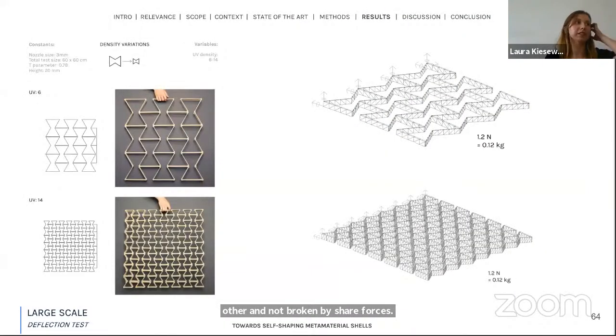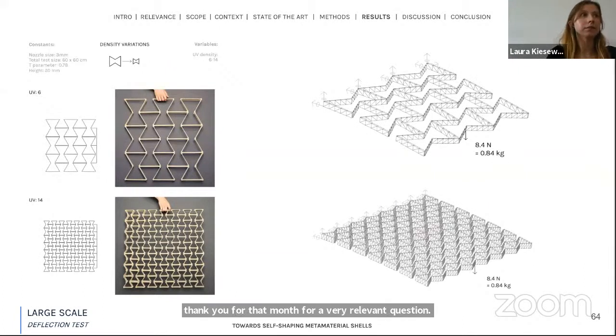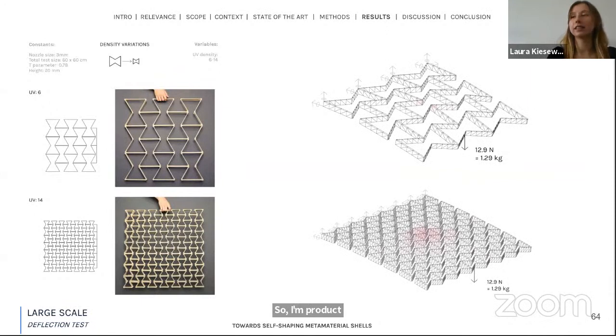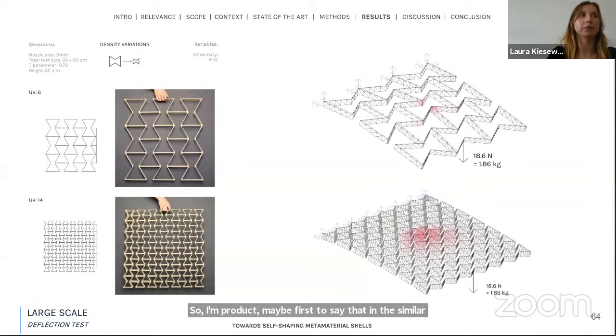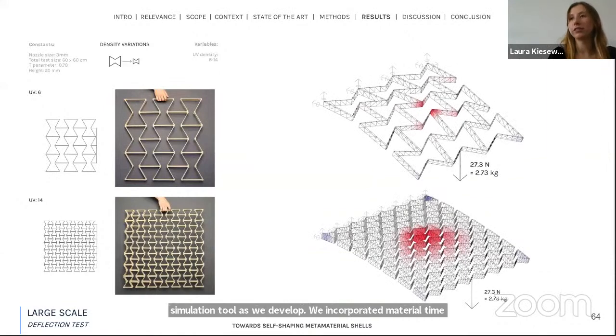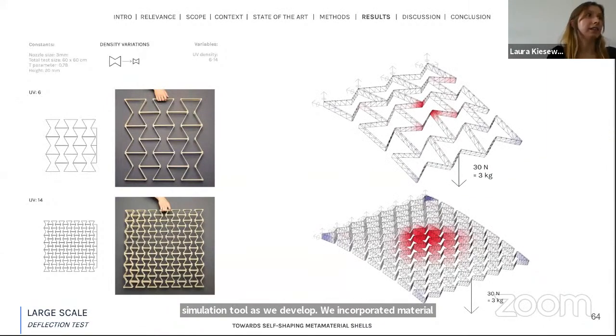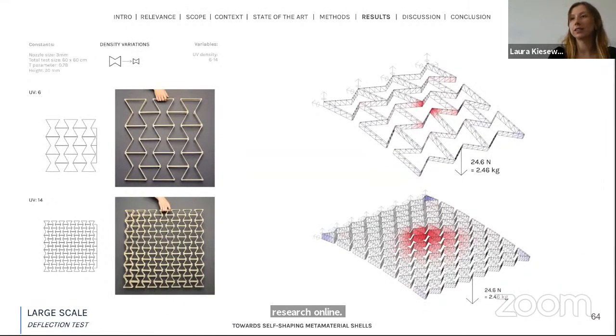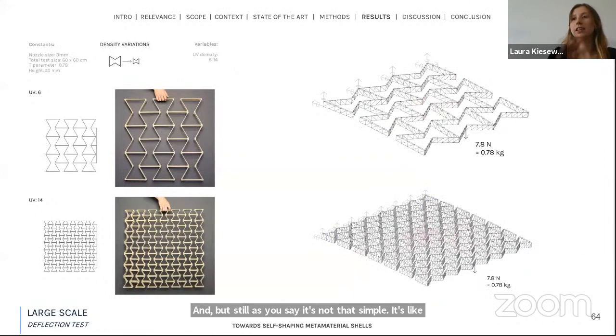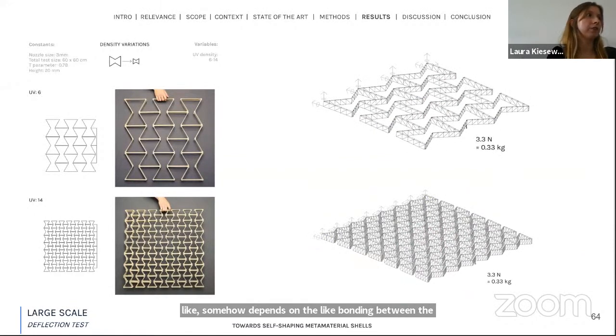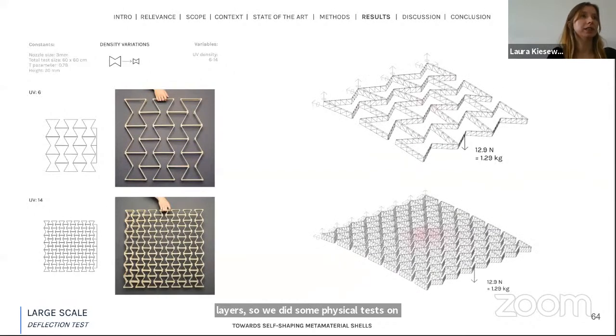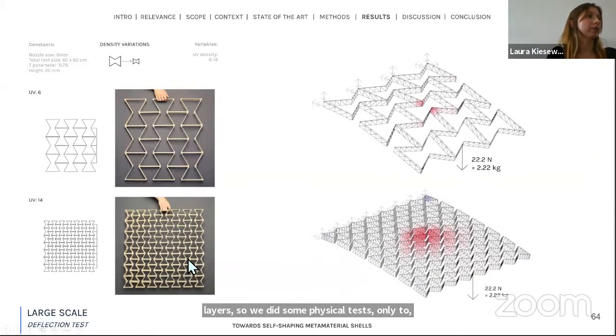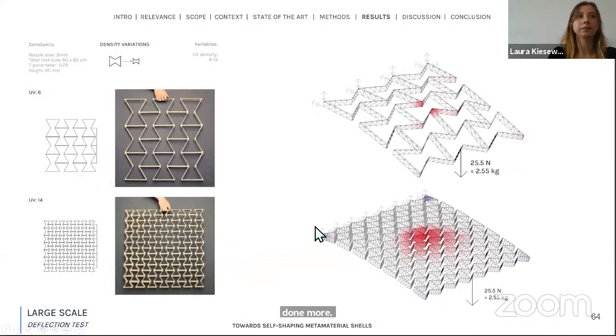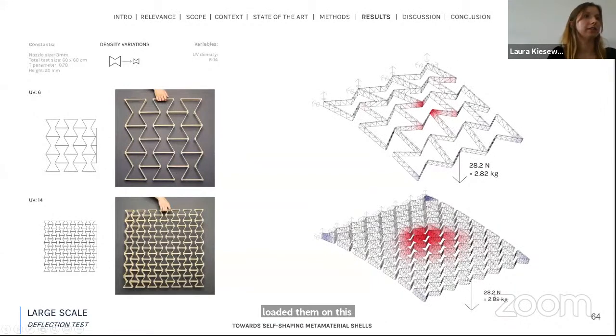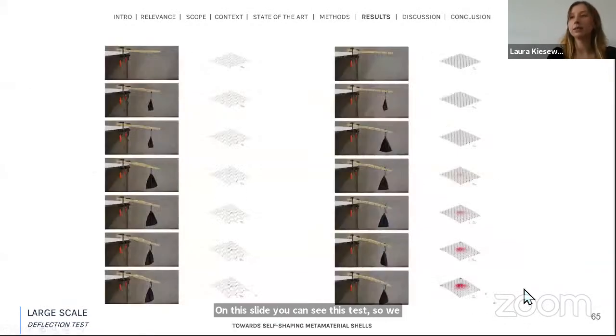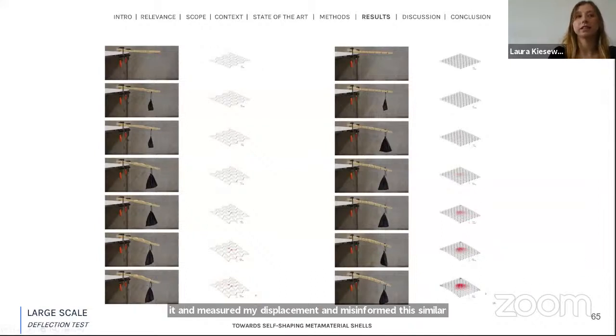Thank you, Philip. That's a very relevant question. So for that, maybe first to say that in the simulation tool that we developed, we incorporated the material parameters or the material values that you can research online. But still, as you say, it's not that simple. It somehow depends on the bonding between the layers. So we did some physical tests, only 2, unfortunately, but if we had more time, we would have done more. So with different densities and somehow loaded them. On this slide, you can see this test. So we put weight on it and measured the displacement, and this informed the simulation that we developed.